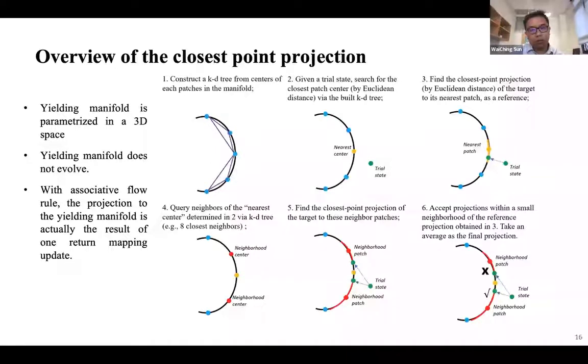Okay, so this would give us not just a good representation of the yield surface, but more importantly, we found out that this has a benefit in dealing with a material that has very sharp changes in the plastic flow directions. So we will introduce a closest point projection to deal with the non-smooth yield surface problem.